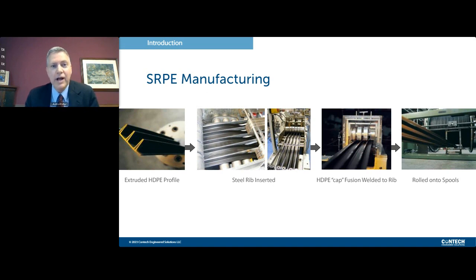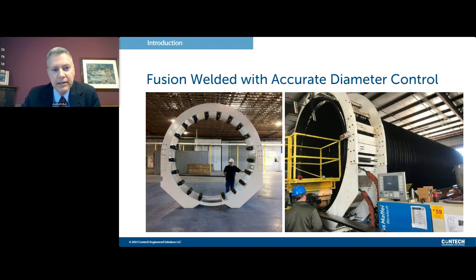At that point, the profile is wound onto a large spool, which can be stored, or it can be sent to another plant for manufacturing into pipe. And when it's ready to be made into pipe, we use a winding cage and a fusion welding machine. And we have individual winding cages for most of the diameters in 6-inch increments from 30-inch to 120-inch. And at that point, the profile is unwound off the spool. It enters the winding cage. The edge of the profile overlaps with the preceding edge of the profile, and it is fusion welded together to form a very strong pipe wall. And this pipe slowly rotates onto a rolling table, and when the desired length is met, a saw engages from the bottom and it cuts the pipe to length.